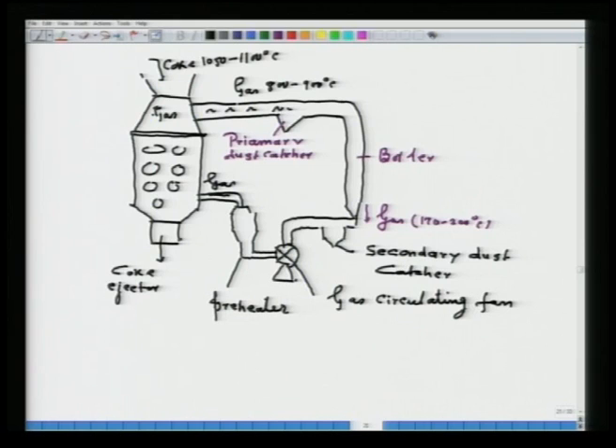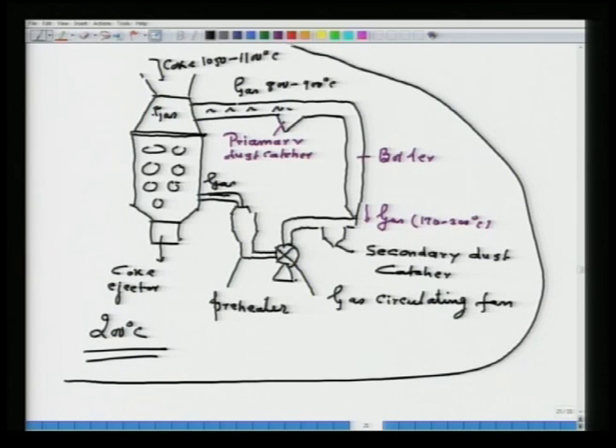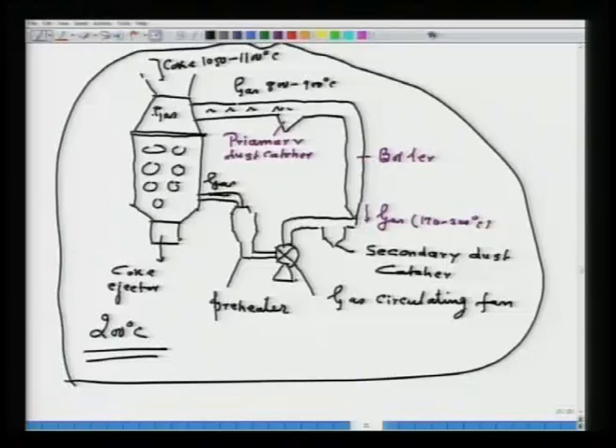And the coke ejector, now the coke comes out at around 200 degrees Celsius. So, you see, by developing this particular technology, which is called the dry quenching technology, you have contributed not only to recover the sensible heat, but also you have created an environment where steam can be produced and turbine can also be run. So, this is a typical example of this.